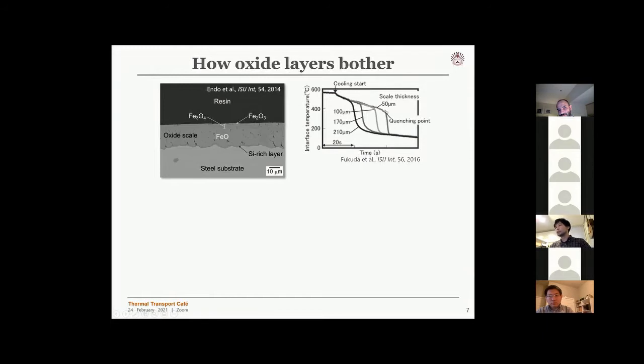This is the sample with oxide layer. The scale thickness is around 50 microns, and you get the quenching point around 400. If you have thicker oxide layers, then you have a much higher quenching point.